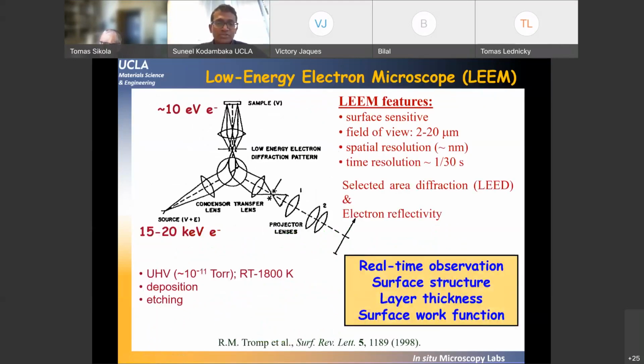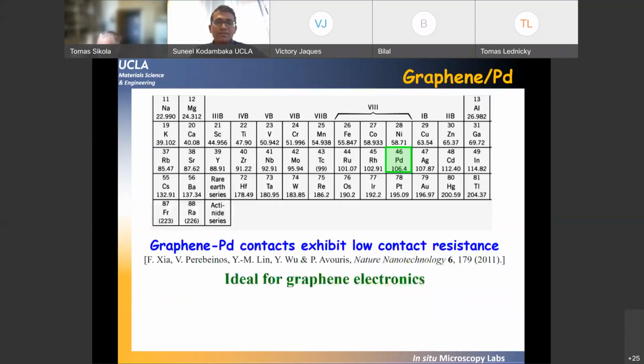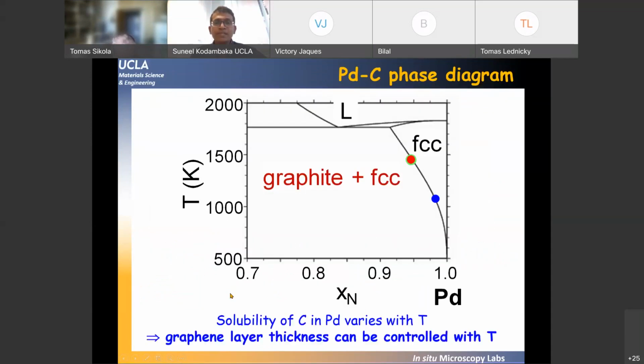And so I'll first present the use of LEEM for studying structure-property relations and growth kinetics for graphene growth on palladium-111. We have been working with palladium for a long time, and it so happens that palladium is an ideal contact for carbon nanotubes and also for graphene, so it could be good for graphene metal contacts. And palladium, like other similar transition metals, has good solubility for carbon.